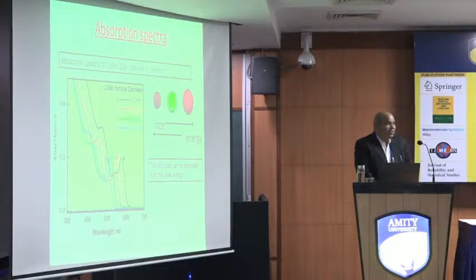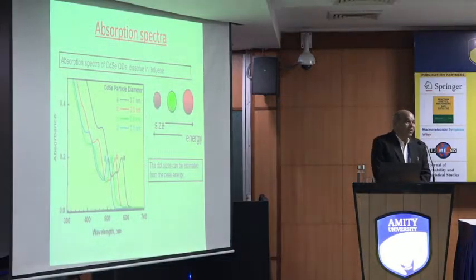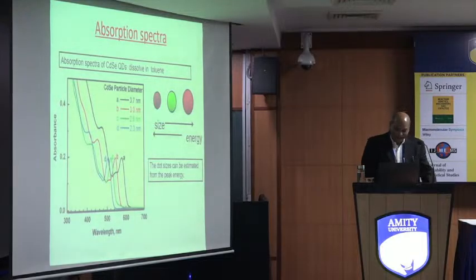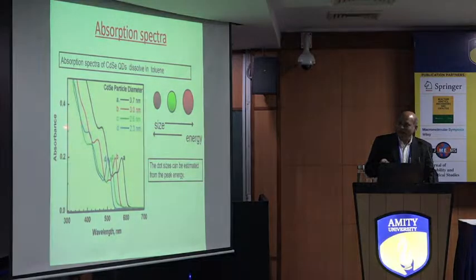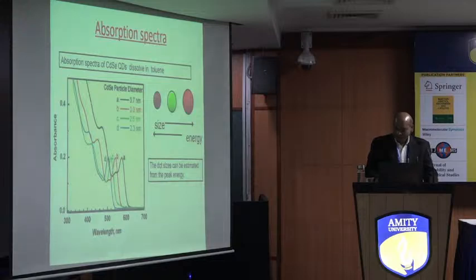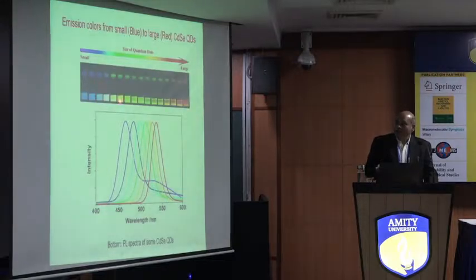And now the question is, how do you know whether this is a quantum dot or not? Experimentally, by a very simple experiment, absorption spectra. If you are able to get this peak, known as the exciton peak, then you can say this is a quantum dot. This peak also changes with the size of the quantum dot. You can see it here for the CdSe quantum dot. Also the absorption spectra, from small quantum dot to large quantum dot, is systematically going to change here.